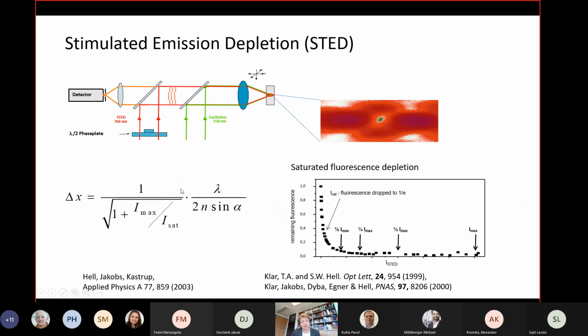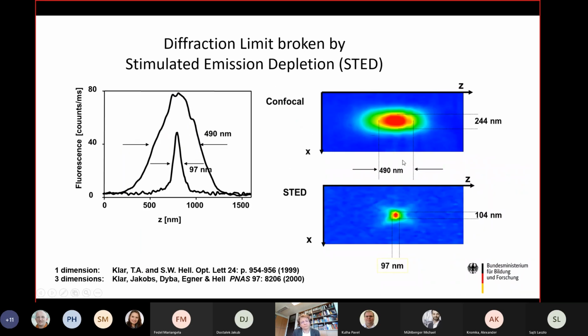It shows that the traditional diffraction limit gets a prefactor, and the prefactor is essentially 1 over the square root of the applied intensity. And when you ramp up the intensity, you can improve the resolution quite a bit. It actually worked. We showed that around 2000, the confocal counterpart, and the same experiment when we switch on the STED beam. In those days, 20 years ago, we showed 100 nanometers in all directions. Meanwhile, the Stefan Hell group is down to below 10 nanometers in optical imaging.